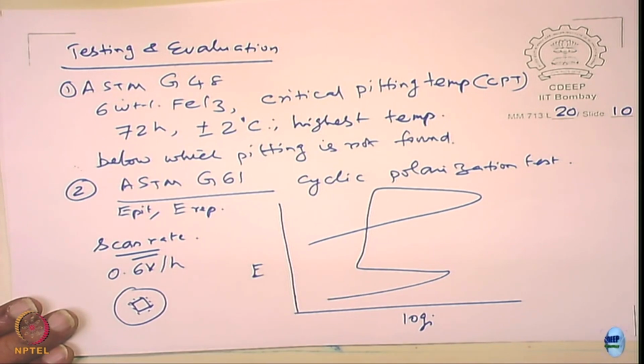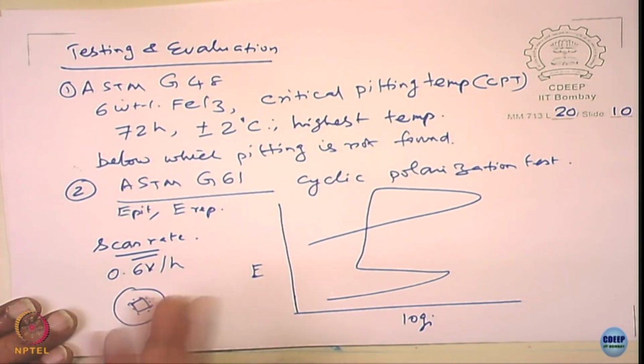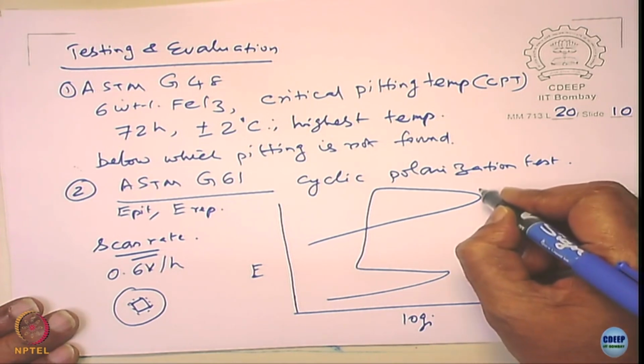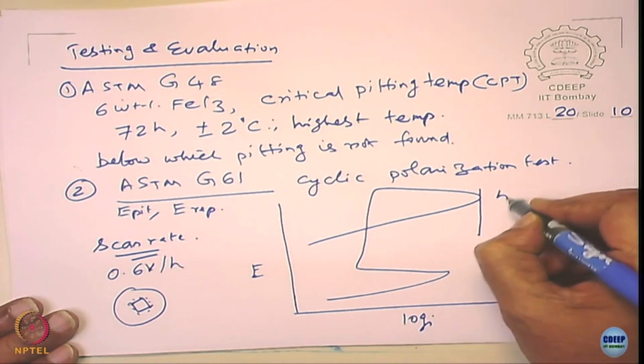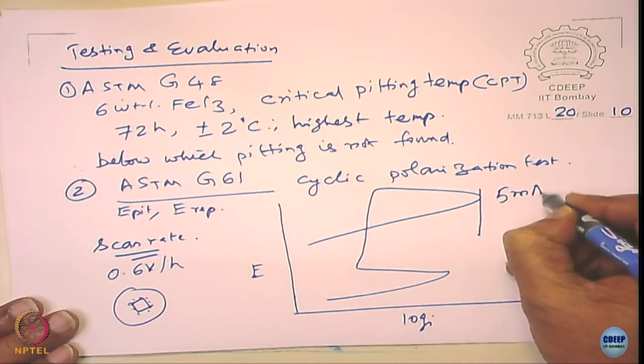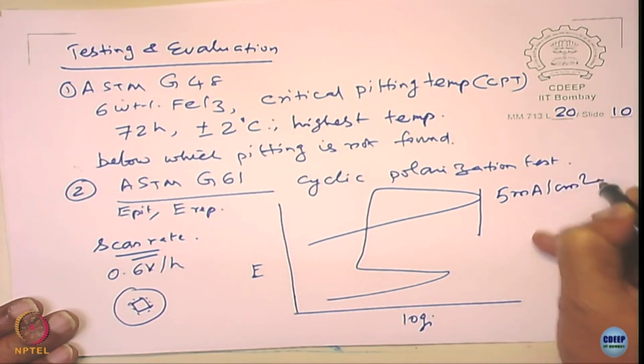In our lab, we apply a small bead of epoxy resin, so that the interface is protected from that. There are also special electrochemical cells available. I think we will not discuss here. You can see them in the literature actually. What is more important is that this reversal current, what we talk about here, is 5 milliamperes per centimeter square.